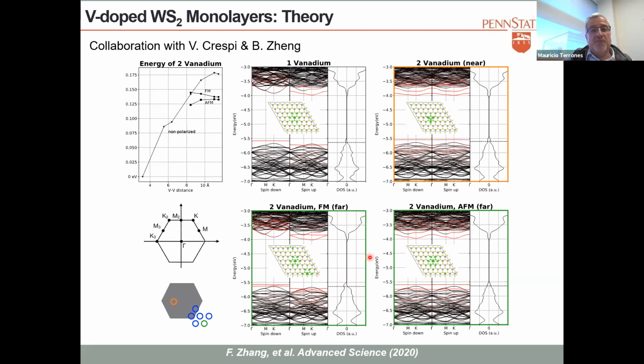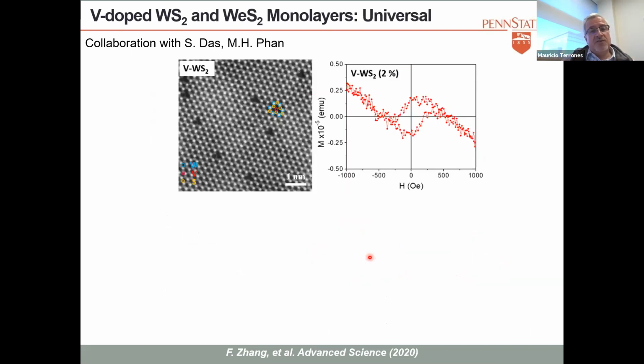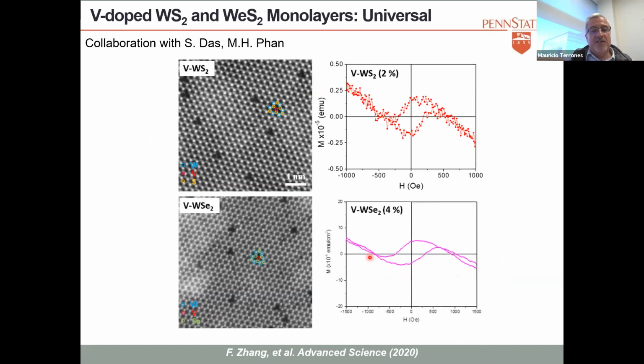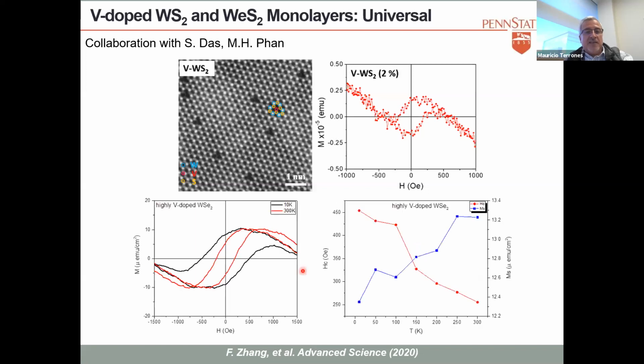I think this is very important. We have done this with tungsten disulfide, and we have observed this with tungsten diselenide with 4%. We did it in a different furnace, actually a different process, for making this vanadium doped tungsten disulfide. Also, we did it with vanadium doped tungsten diselenide, and the nice thing for tungsten diselenide is that the coercive fields at room temperature are much higher than tungsten disulfide. So this is a very interesting material, and we can see it happened with tungsten disulfide and tungsten diselenide, and we have a couple of papers on this. So this is a nice way to change the properties of the material.